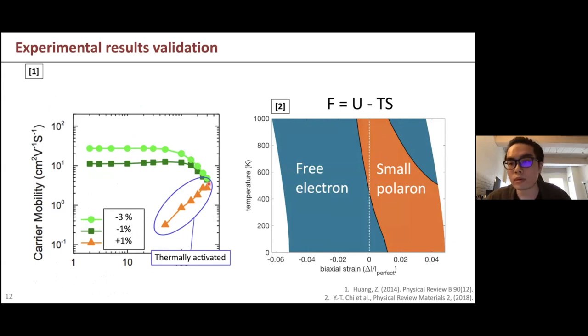So if you remember how small polaron transport works, it hops from one titanium to the other. So it has an energy barrier it has to overcome. The energy barrier is not high, but still it is in the exponential term. So when you do the Arrhenius equation fitting, you can get the activation energy. And that's what we found here from the experiment.